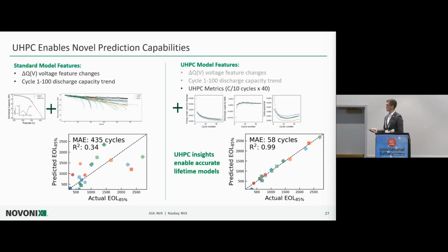So using some standard modeling features, primarily from the Severson work, that's really famous in the field. So looking at delta QV voltage features and changes in the first 100 cycles, and then the discharge capacity trend in the first 100 cycles. This does a very poor job at estimating the cycle life using these models.